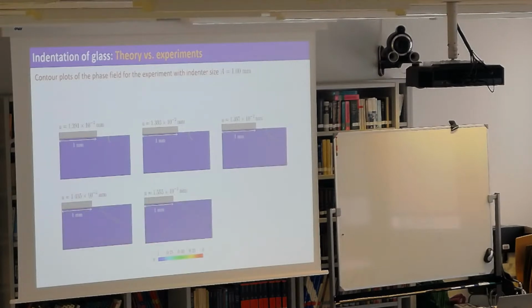All right. So let me show you what happens. So this is a contour plot of the phase field, V, right? V equal to 1 means no crack, 0 means crack, right? So what we see for this particular case of the indentation size is that a crack nucleates very fast. I mean, as fast as we can tell numerically, this happens instantly. A crack that is at a given distance, right, from the indenter and has some age to it. And as you continue to apply U, remember that this is driven in displacement, right? Then you turn into a cone crack and then you propagate. And that's essentially what happens in all the simulations. Of course, the value at which things happen and the distance and all that changes, right? But I'm going to show you now the comparisons with experiments.